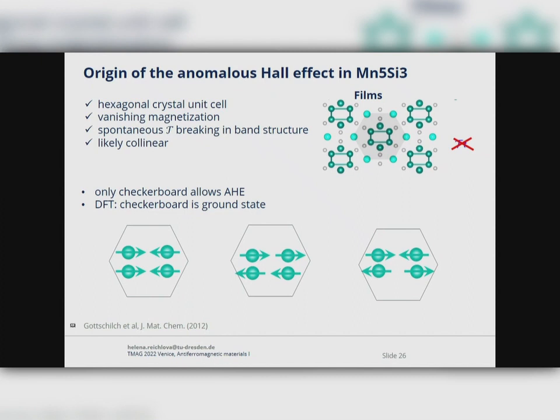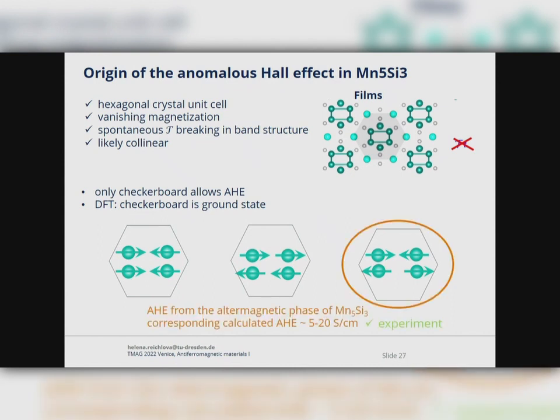And by the DFT calculation, this state is calculated as the ground state. And interestingly, the calculated anomalous Hall effect gives us approximately the same value of the anomalous Hall conductivity as we measure in our experiment.